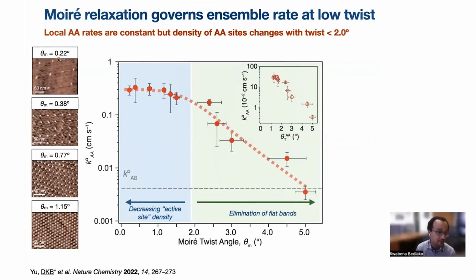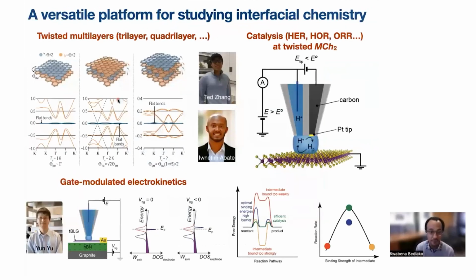So we're very excited about this platform now for studying interfacial reactivity, where we have the ability to create these flat electronic bands so that we can probe the effect of these types of electronic structures on electrochemistry, and understand real systems, even say transition metal surfaces that have very narrow d orbital based bands, for which theory has not yet caught up to the real experimental system, because there's a knowledge gap in having these controllable materials where you can systematically tune the electronic structure and measure the electrochemical behavior. So we're very excited about this platform.